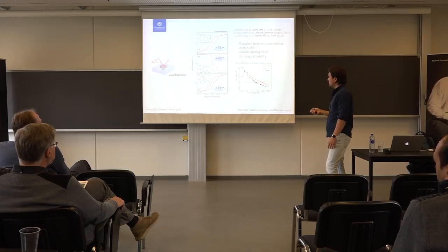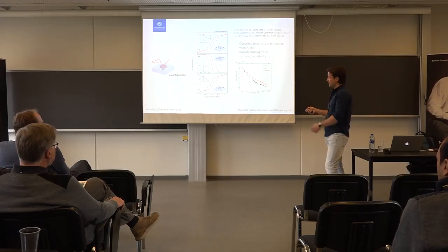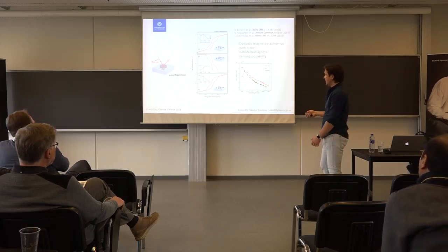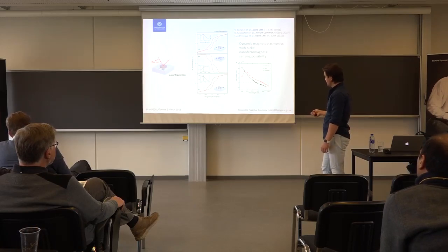You can also measure that spectrally. So you can collect these loops at every single wavelength. This dot, the height of that data point, is actually the difference between this saturation point and this saturation point, except that here they are normalized. But like I mentioned, they actually have a different height. All these loops have different height, which means the rotation of polarization is different in all the systems, and that is actually expressed here. So the Kerr rotation is different at different wavelengths.